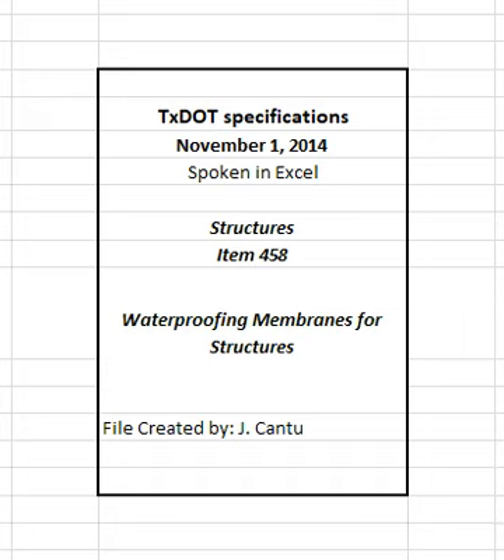2.2.1 Type 1. Butyl rubber membrane applied to a surface with a proper adhesive without protective planking and in accordance with the details shown on the plans. Provide a minimum thickness of 1/16 inches unless otherwise shown on the plans. 2.2.2 Type 2. A single asphaltic primer coat and 1 mopping of asphalt. 2.2.3 Type 3. A single asphaltic primer coat and 2 moppings of asphalt.